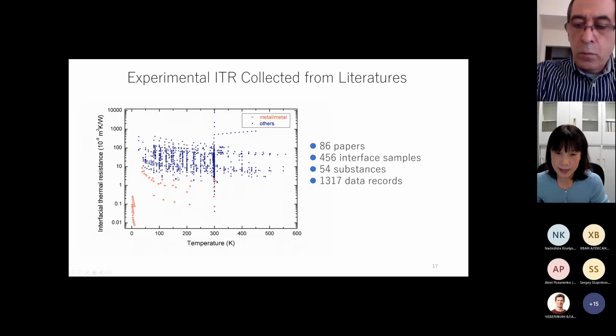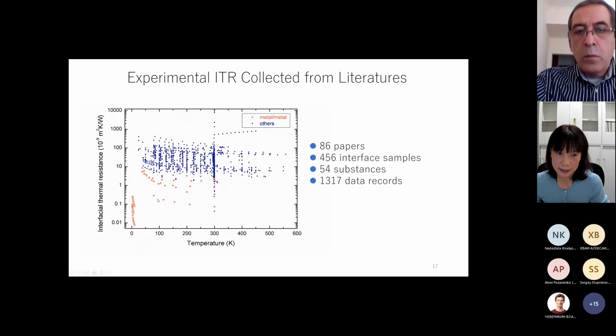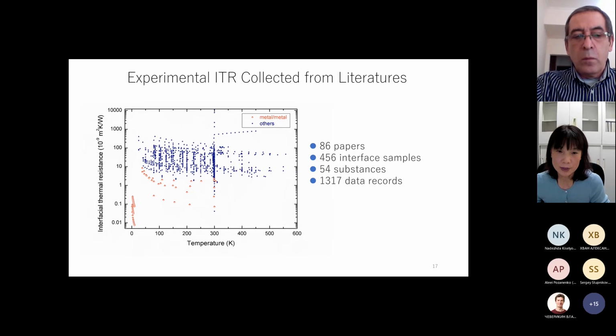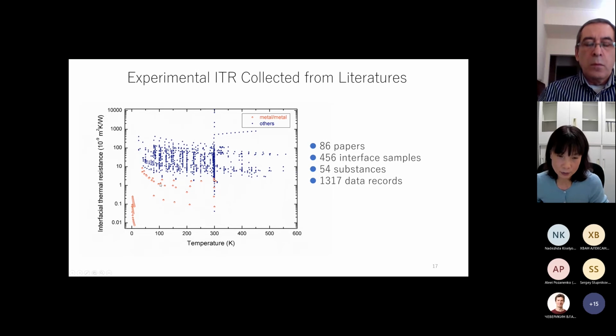As shown here, the red points show the metal interface, and the blue points show the others. In the metal interface, the energy carrier is electron. But for the other case, phonon is the main energy carrier. As we can see clearly, the electron has much lower interfacial thermal resistance than phonon. But in this study, we want to find the interface with high thermal resistance. So that's why we use only the blue data.